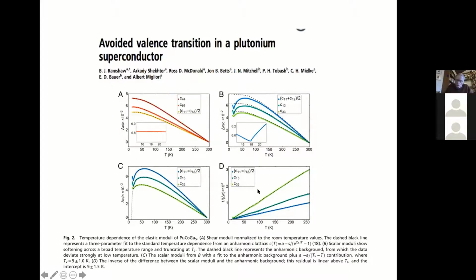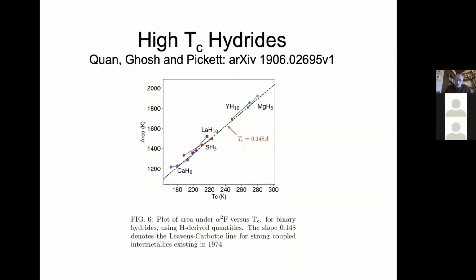It reminds one of what one sees in ferroelectrics, that extrapolates to 0 at 9 Kelvin, which is actually below the 18 Kelvin transition temperature. And so it seems that what happens here is that the superconductivity, in this case, similarly to what we've seen in the previous examples, is to somehow quench this lattice softening on cooling down. Again, part of a very similar pattern in superconducting materials.